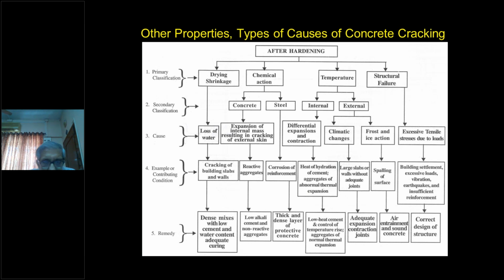Depending on the quality of the mix, I'm saying quality of the mix, also on the grade of concrete, also on the thickness of the pavement and road which you are constructing, the joints have to be designed at a particular spacing. If the spacing, for reasons best known to the engineer, are far apart and not adequate, then concrete will crack in between the engineer made joints. So it is always better. Another strong recommendation from me is always cut the joints in such a way that the panels between the joints are square, not rectangular. I will show you what happens when you have rectangular panels.